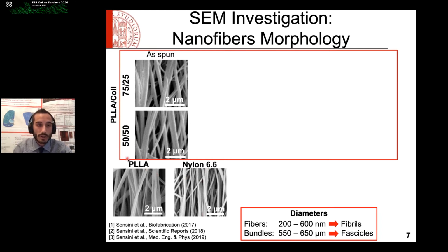As you can see, all the nanofibers were homogeneous, preferentially axially aligned, with an average diameter that resulted, both for the nanofibers and the bundles, in the same range as the fibrils of collagen and the fascicles of tendons and ligaments.